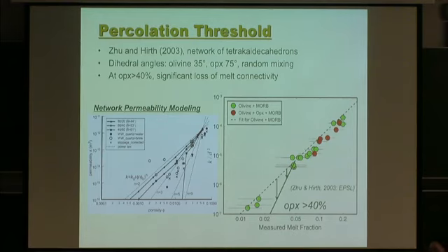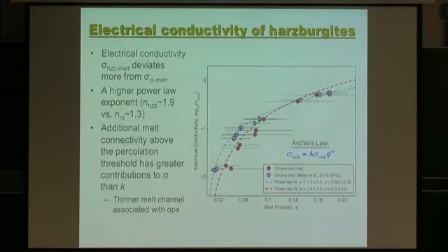it's just a strict one-plus-one mixing. There's no interaction between the melt and the melt redistribution. So what we think is happening is a melt redistribution, which is a large part of my talk, in that we also calculate electrical conductivity, and you see the conductivity actually changes a little bit, has a measurable change.